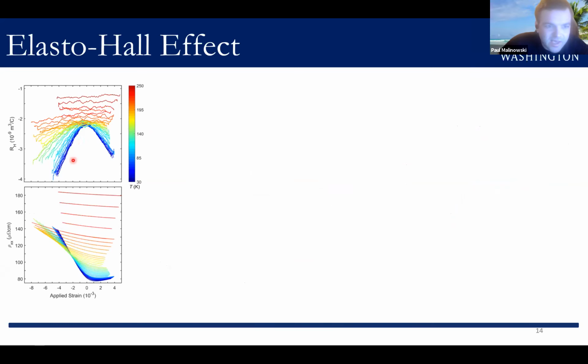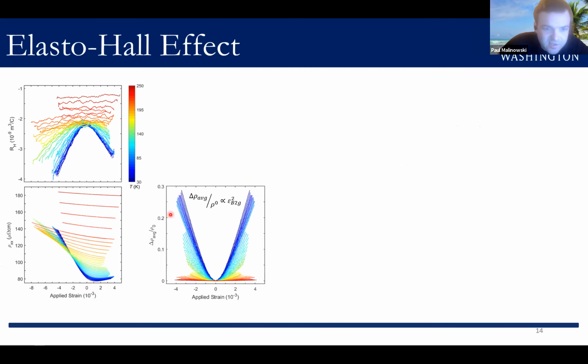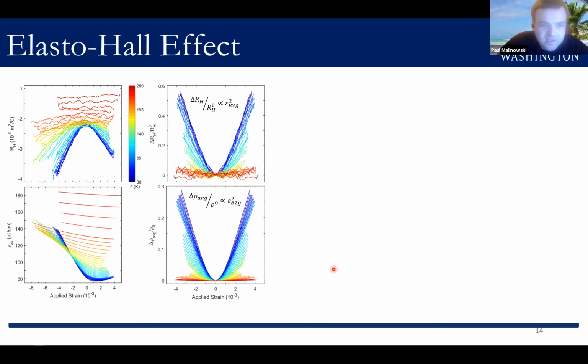So we can compare this behavior with the simultaneously measured elastoresistivity, shown here on the bottom. And this also exhibits a strong nonlinear component at low temperature. And by symmetrizing this data about zero strain, we can isolate the change in the average in-plane resistivity, which by symmetry must be proportional to the square of the anisotropic B2g strain. And we can compare this to the normalized change of the Hall coefficient. So what you see here is that both of these isotropic quantities have a response to strain that is dominated by a strongly temperature-dependent nonlinear response to the B2g strain.